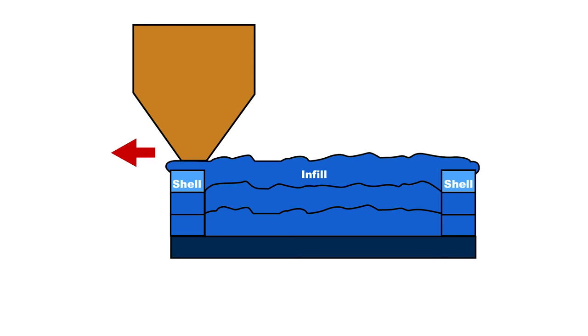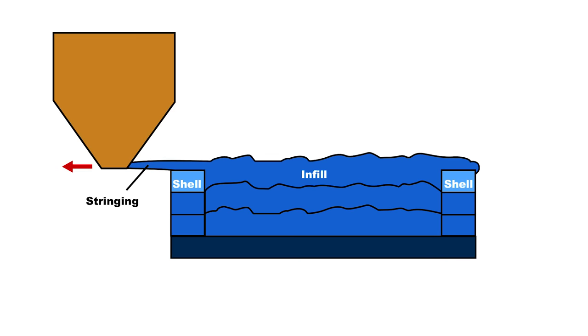Other times people contact me and will say, hey, I'm trying to print a miniature out. I've got retraction cranked up to 7, 8, 9 millimeters, and I'm still getting stringing. Well, the reason is, it has nothing to do with your retraction. You're printing a solid mini. That plastic has nowhere to go, and when that nozzle contacts it, it's dragging it off as a string. It has nothing to do with your retraction, has nothing to do with the filament inside the nozzle. It's all of the excess filament you're printing outside of the nozzle that's causing this. So again,